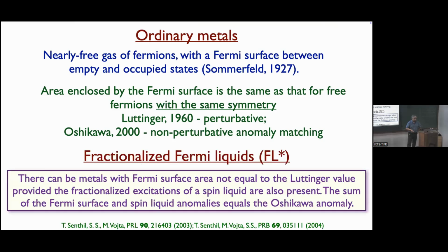Then around 2000, we proposed that there's actually a loophole, which is that the low energy theory could be more than that of a Fermi surface. There could be a spin liquid. And spin liquids also have anomalies associated with the filling of the electrons. The filling is very rigidly equal to the density, which is 1. And so the sum of the anomaly of the spin liquid and the Fermi surface should add up to the Oshikawa anomaly.